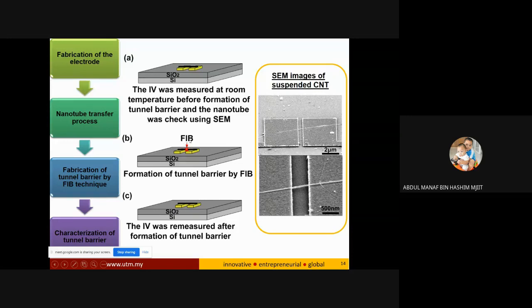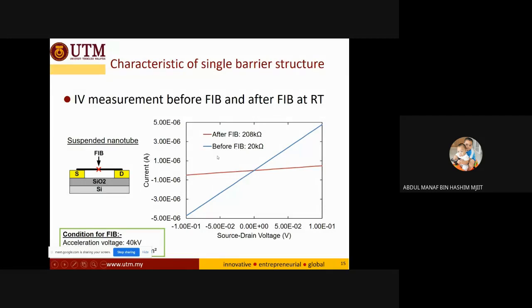Here we put it in the FIB system, and then we irradiate it with the beam. Of course, here we study the dependency on the ion dose. This is an SEM image of the suspended nanotube on the electrode. After we fabricate this structure, we do a characterization. Here we study the barrier before and after irradiation using FIB. You can see that the resistance of the nanotube increases after the irradiation, meaning that the barrier has been formed.